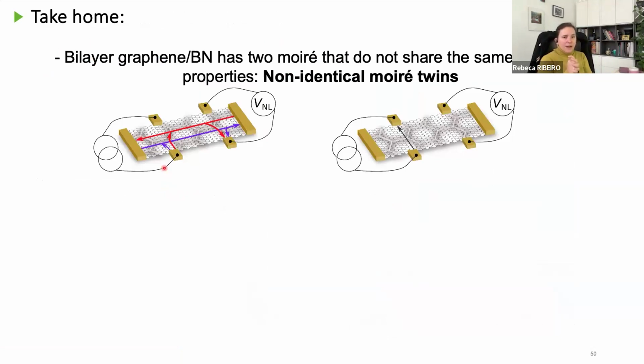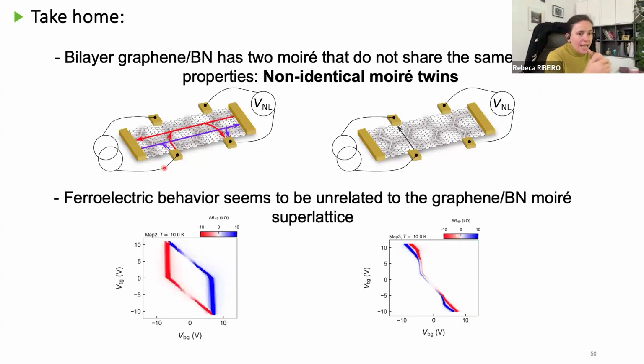talk: bilayer graphene aligned with boron nitride has 2 different moiré superlattices. The observation of these different electronic properties of moirés in the same material is only possible because we can change the alignment of the layers in situ, and because we have this dynamical control of the layers. And we can observe this ferroelectric behavior, which we are looking forward to observing in AFM images very soon as well, which is not, in fact, differently to the proposal of the MIT group, this is not related to the moiré superlattice.